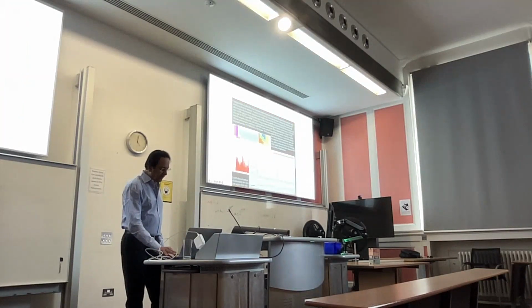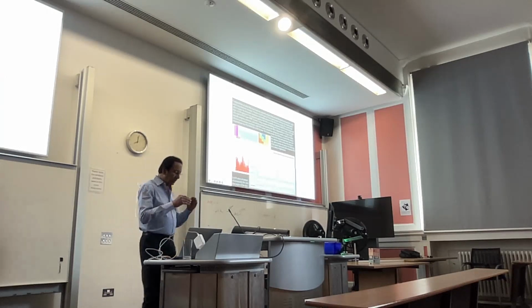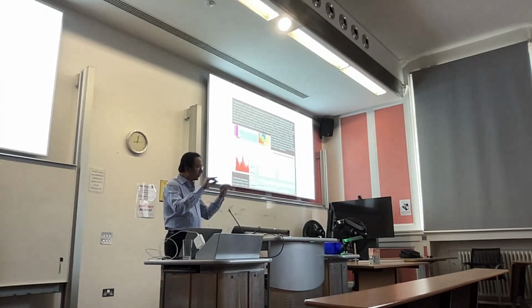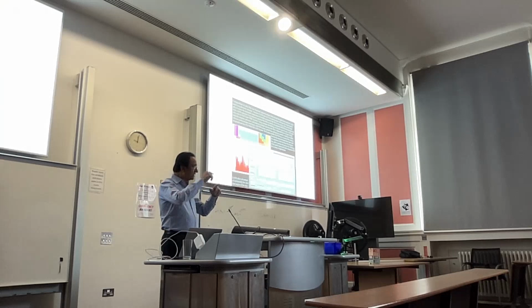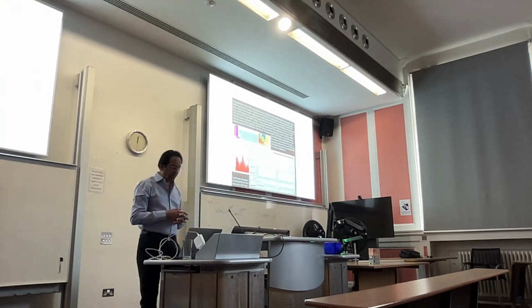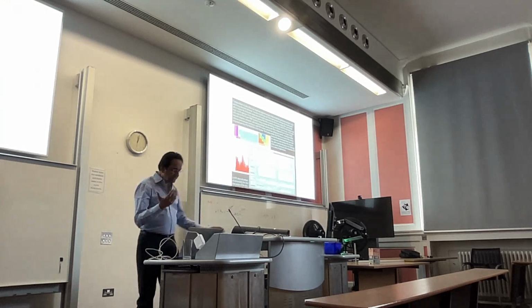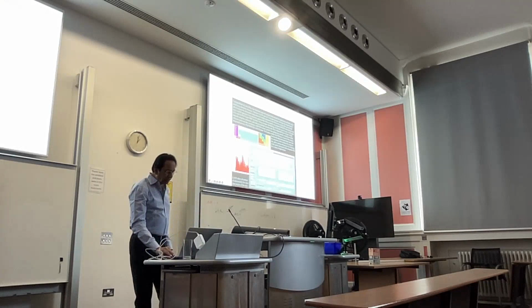So here are the X-rays actually collected as the film is being grown. You can see this is the Bremsstrahlung level, which is like the background in the X-rays. And you can see a lot of peaks. These peaks are the characteristic X-ray peaks of the films and so on. The problem with X-ray spectroscopy is that if I take a finite thickness of film and look at the X-ray that's coming out, this X-ray is subject to absorption by the layers above. So the X-ray coming from the bottom layer is absorbed by the layers above it, and therefore you have to correct for it. And you don't quite know how to do that in an easy way.